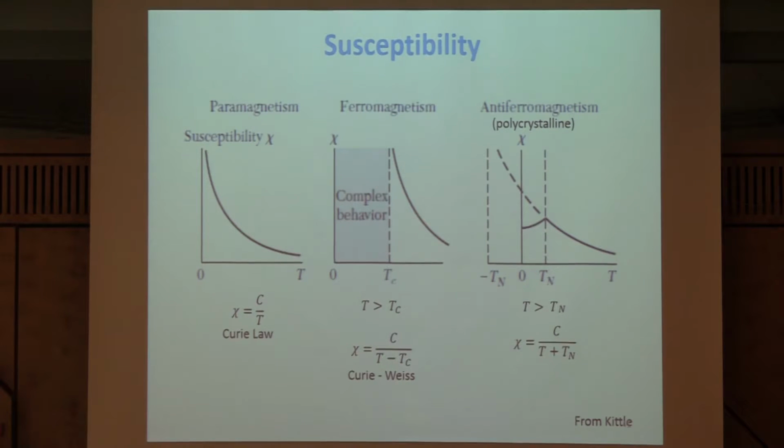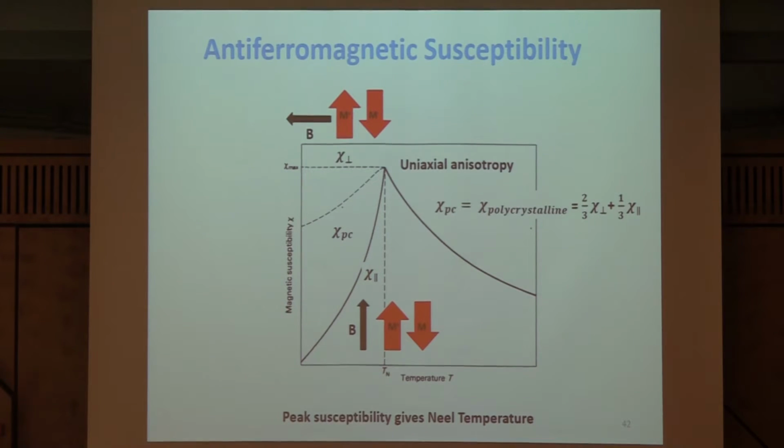The susceptibility. Okay, we saw this in a form in Thomas's earlier on. One nice thing is that the susceptibility of an antiferromagnet can have a fairly characteristic behavior. It's not definitive, so ferrimagnets are rather similar. Obviously paramagnets have a divergence at 0 K. You've got a divergence in ferromagnets at finite temperature, at the Curie point, but you only have a cusp at the Néel temperature. In fact, you don't necessarily have a cusp because it depends where you apply the field with